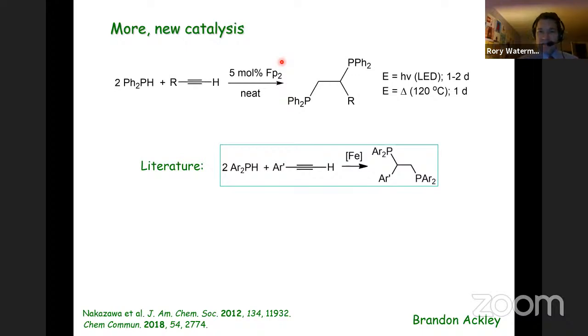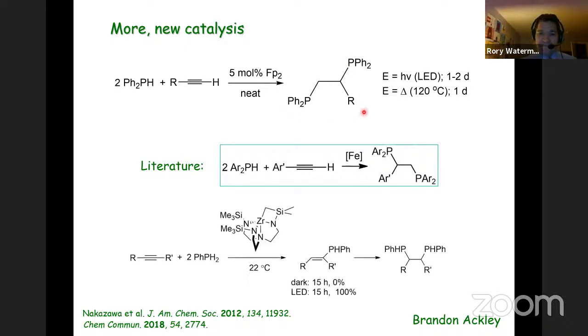In Nakazawa's case, there's liberation, or proposed liberation, of that methyl after migratory insertion with the carbonyl ligand. In that case, the reaction appears to be slow based on coordination of the intermediate to the iron. Because both carbonyls are retained at iron, we think that's the reason why this catalysis is substantially faster than the original. And just as a reference then, now what we're seeing is fast conversion to the secondary system. We also can build the primary systems, which we could conceivably functionalize at phosphorus. And so there's now actually a whole stable of these compounds, and they're relatively accessible.